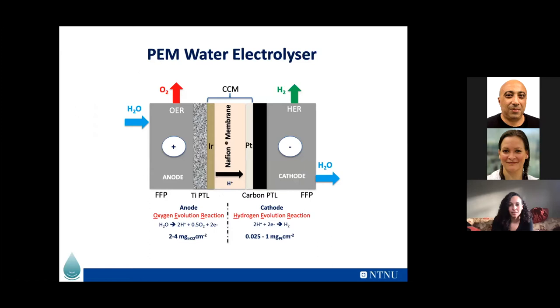So what you have really is the oxygen evolution reaction, the OER, which is one of the sluggish reactions here, in contact with iridium oxide. You get about two to four milligrams of iridium oxide per square centimeter in terms of loading. In between, you've got a Nafion membrane. And on the cathode side, you get the hydrogen evolution reaction, where you get some loading of platinum between 0.025 to 1 milligram per square centimeter, and you've got your hydrogen production on that side.